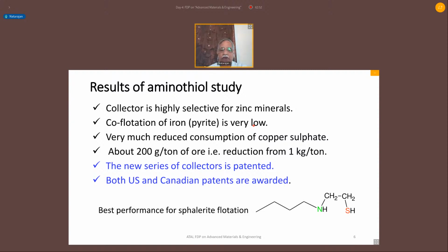And the copper sulfate consumption is very much reduced. Unless the zinc mineral is suppressed for the flotation of some other mineral, we need activation. Otherwise, even activation by copper sulfate is not necessary. However, comparing with the current mill process, we need just 200 gram per ton, whereas the present mill processes use 1 kilogram of copper sulfate per ton. Now we have reduced it to 200 gram per ton of the ore. That means we reduce the copper sulfate consumption.